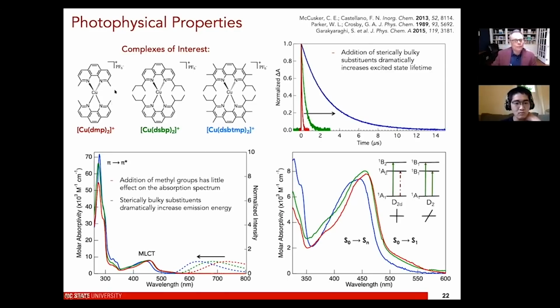So the methyl group, really, if you look at the absorption spectrum of this, it's red. So you see how this has a tail, and if you blow it up, you see this tail. What that's telling you is in the ground state, this is exhibiting more of a D2 geometry, which is a little bit distorted with respect to the starting tetrahedral D2d geometry. And the way that this manifests itself is you start to get an allowed MLCT transition when the molecule is a little more distorted.